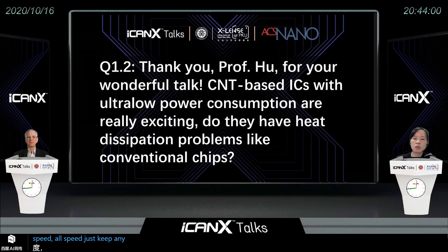We found that the current in the device cannot be promoted further. After the measurement of the device, we checked the morphology of the device on the substrate, and we find that there are some heating issues on the substrate. If we want to further promote the speed, the speed just depends on how much on-state current you can provide in your device. So if we further promote the on-state current, then there will be some issues related to the heat dissipation.